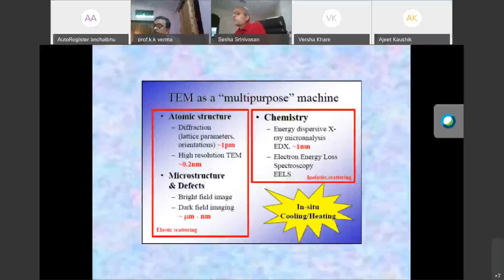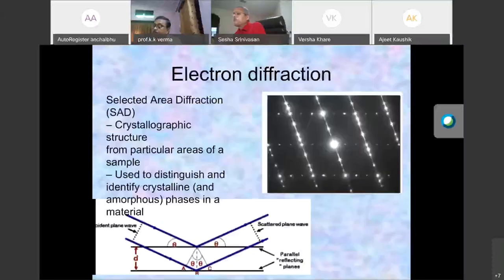So this is the diffraction pattern, which is a very specific character of the electron microscope, because the wavelength is so small that it is close to the interatomic distances of the material, and therefore this is the possible condition for diffraction, and therefore diffraction will take place. And by this diffraction, very similar to X-ray diffraction, you can know about your material details, your metallurgical information and all this.